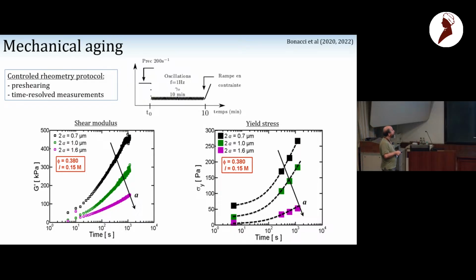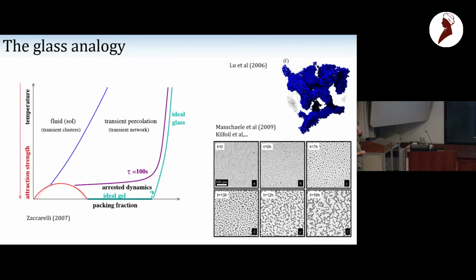So we have rheometry protocols, and so you can measure here the shear modulus of the system. So you have here systems of microspheres of different diameters, and you look at the shear modulus as a function of time, and you see there is a dependence on the size of the particle, and you have this logarithmic aging. You take the yield stress also. What people do is that they pre-shear the system and then they do very small oscillation to get to the modulus, and at some point they ramp up the stress and then they get to the yield stress, and so you see an evolution of the G prime and the yield stress.